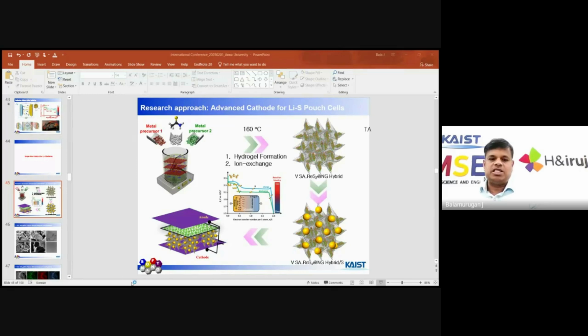And finally, we use it as a lithium sulfur cathode. After fabricating the material, we have to intercalate the sulfur, about 80% sulfur with our catalyst material, maybe 20%. And finally, we make the cathode and we make the device to get the higher energy density and power density.